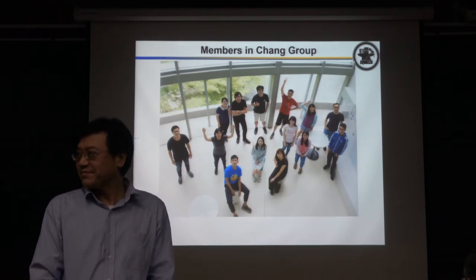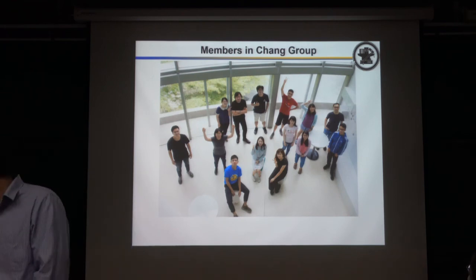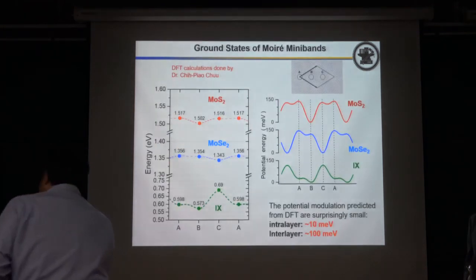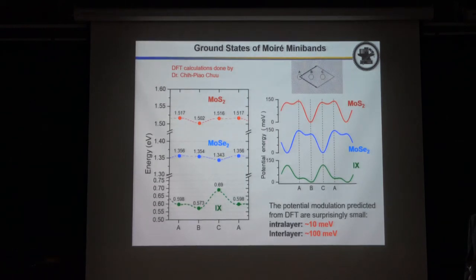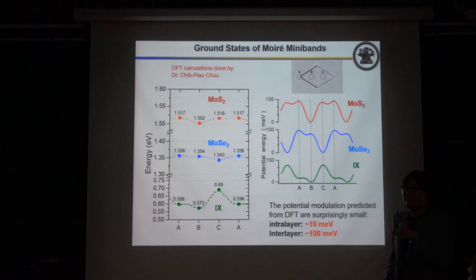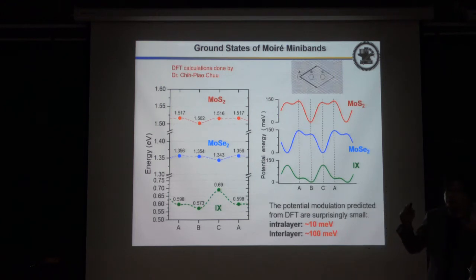Okay, on the first part, for the growth on the metal, could you also give some remarks on why copper 111 is chosen for boron nitride, whereas gold 111 is chosen for another? That's quite simple, because copper is cheap, but it will interact with the chalcogen atom. So you will form copper sulfide. Any other metallic substrate will interact with the chalcogen atom. Only gold can sustain in the chalcogen environment. Yeah, so that's why we have to use a very expensive substrate.